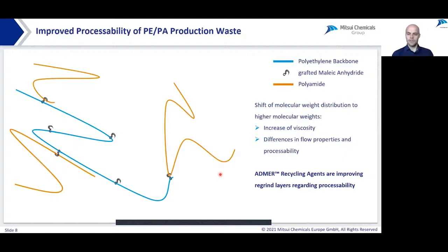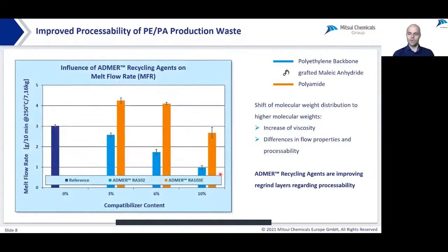We measured the melt flow rate to compare the processability of uncompatibilized and compatibilized material, compared with the reference in dark blue. Even 3% of RA103E, the orange bar, lets the MFR rise about 40%, which is a good indication for better flowability and processability.